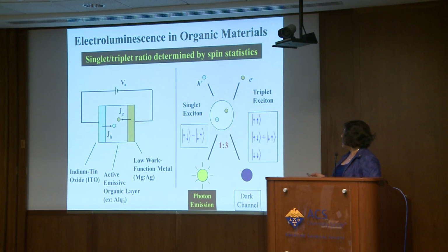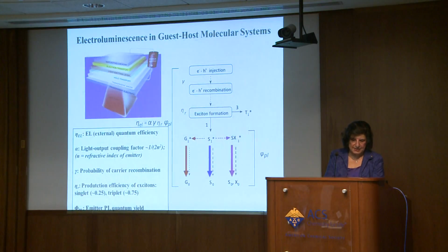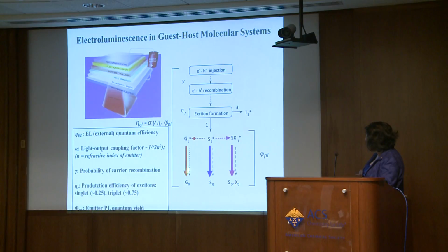And you can form two types of exciton, singlet or triplet. I'm not going to go through the details of that, but the spin statistics dictates that for every one singlet you form, you form three triplet excitons. And my area of research focuses on photon emission from the singlet excitons, which is fluorescence essentially. This just shows you the mechanism in more detail: you get electron-hole injection, then recombination, exciton formation, and this is the path that we want to pursue, the emission from the guest molecule.